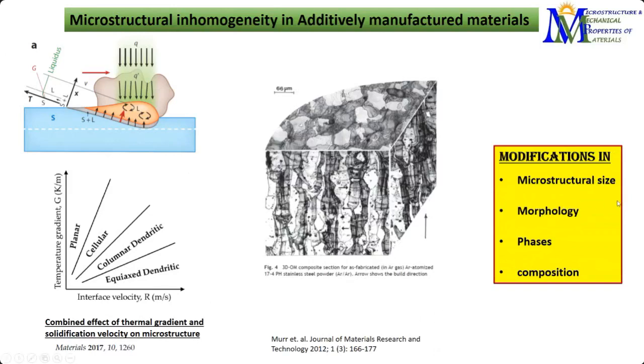And what eventually we get in the additively manufactured component is a modification in the microstructural size as well as the morphology. We may have, even if it's equiaxed grain, fine equiaxed and coarse equiaxed, and columnar grains versus equiaxed grains. We may have different kinds of phases altogether, and not only different with respect to conventionally manufactured materials, but at one zone, top layer versus bottom layer, we may have differences in microstructural size, morphology, phases, as well as composition.